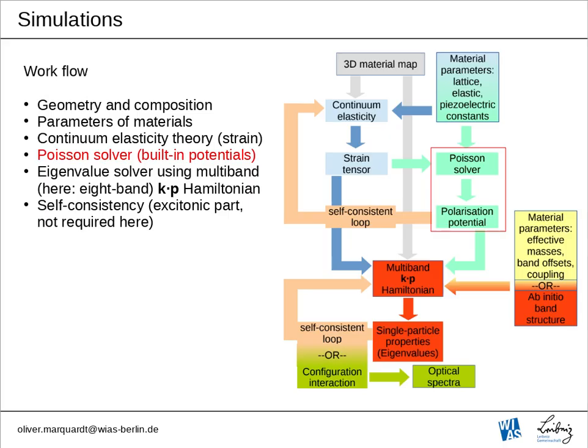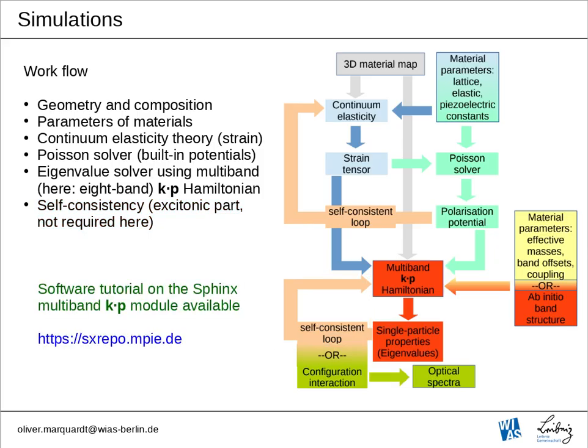In the next step, we run an eigenvalue solver using a multiband, here in this particular case the 8-band k.p Hamiltonian. Let me mention that we are not limited to the 8-band model, so we can essentially plug in any Hamiltonian we like, and this gives us single particle electronic properties, so eigenvalues, wave functions and charge densities. It is generally possible to run a self-consistency loop here at that point, which would give you information on the excitonic part, but given that we have a type 2 system here, we neglected the excitonic interaction because it's extremely small.